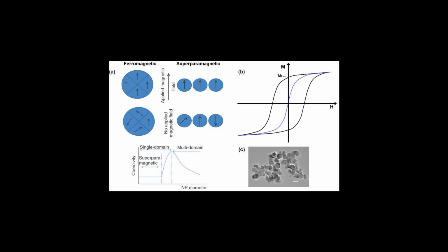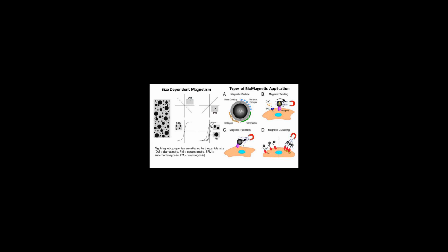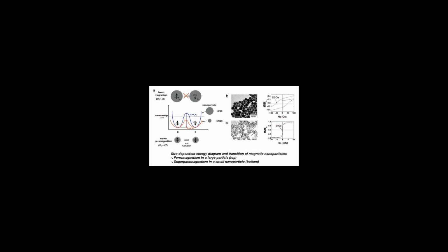Measurements. A superparamagnetic system can be measured with AC susceptibility measurements, where an applied magnetic field varies in time, and the magnetic response of the system is measured. A superparamagnetic system will show a characteristic frequency dependence. When the frequency is much higher than 1/τ_N, there will be a different magnetic response than when the frequency is much lower than 1/τ_N, since in the latter case, but not the former, the ferromagnetic clusters will have time to respond to the field by flipping their magnetization. The precise dependence can be calculated from the Néel-Arrhenius equation, assuming that the neighboring clusters behave independently of one another. If clusters interact, their behavior becomes more complicated.